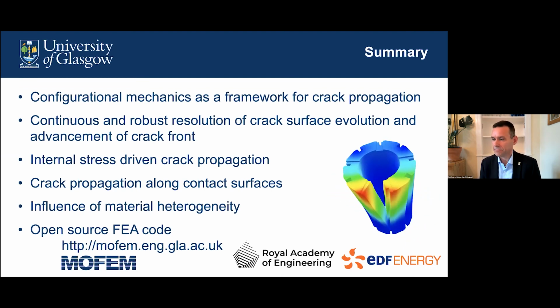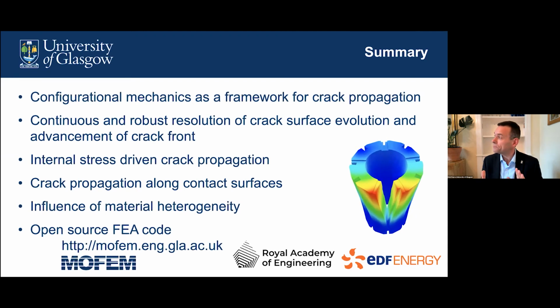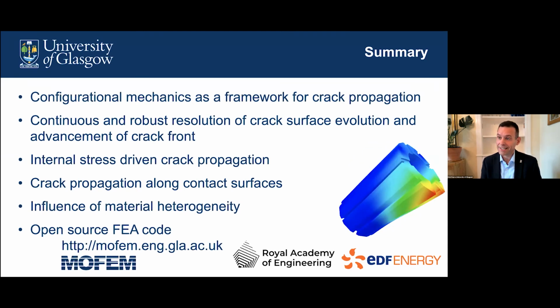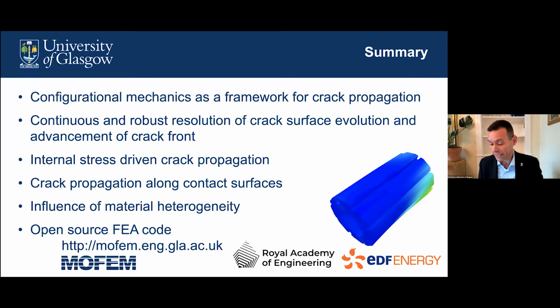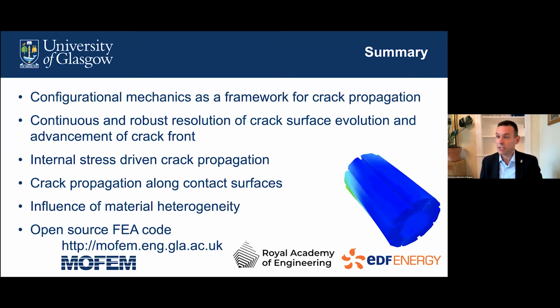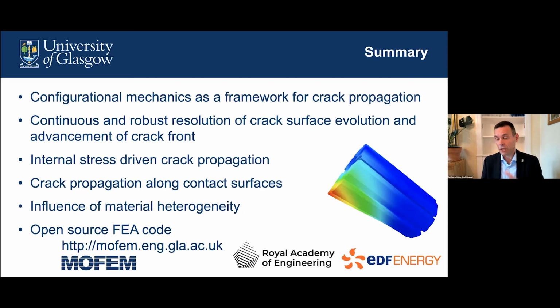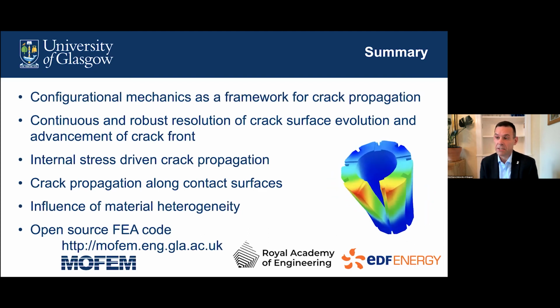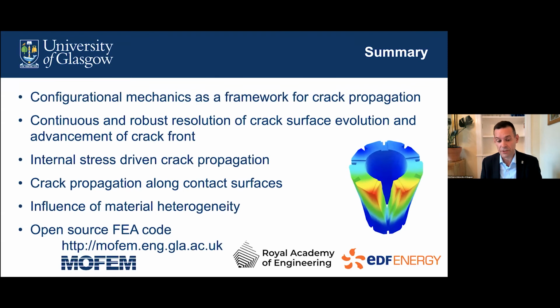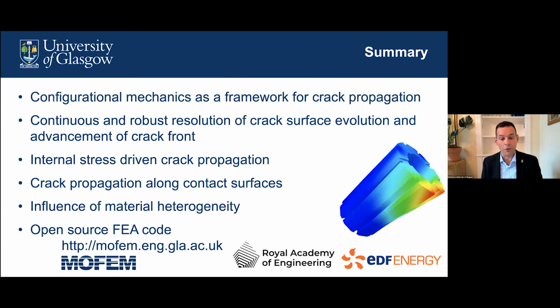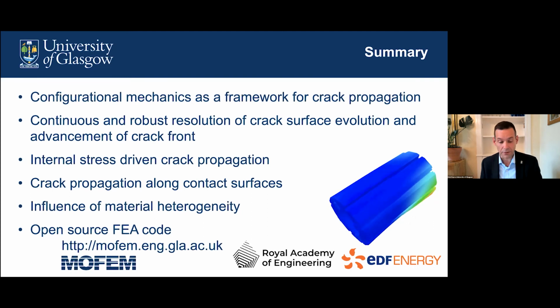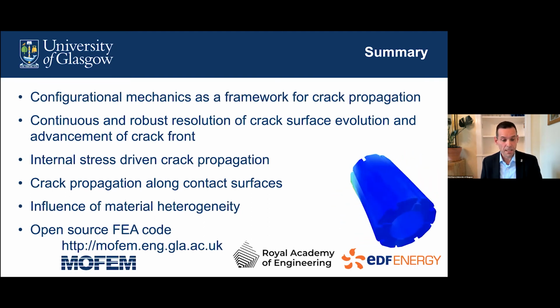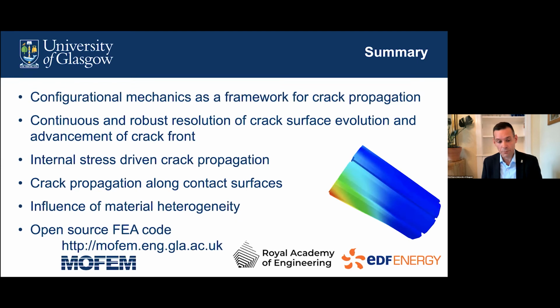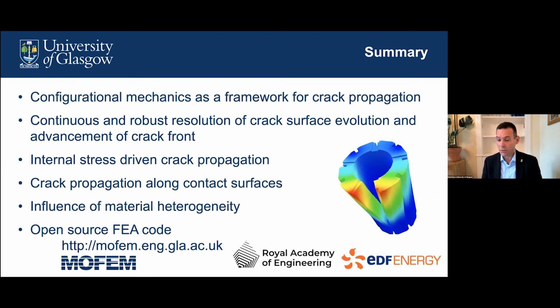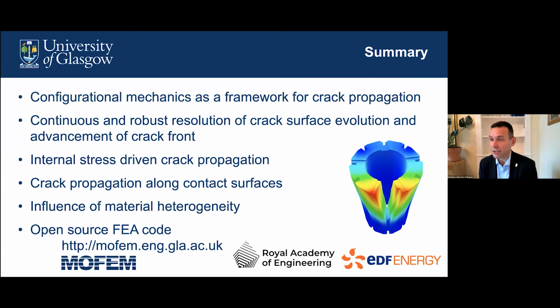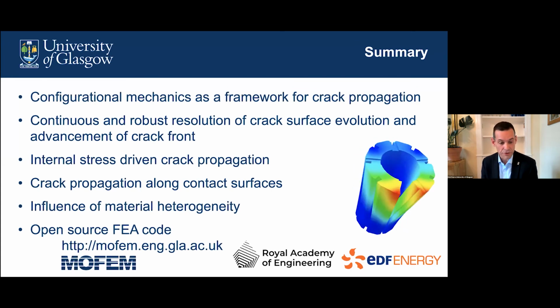We've also briefly looked at material heterogeneity, and for the main problems that we're dealing with, the graphite bricks, we found that material heterogeneity, although it exists, doesn't have a huge effect on the crack path. But we've shown with other problems that material spatial variation of Young's modulus, for example, can have a big impact on the crack path, depending on the severity of the spatial gradient. All of this is implemented into an open source finite element code called MoFem, which can be freely downloaded, and we'll be happy to talk to anybody who's interested in using it.